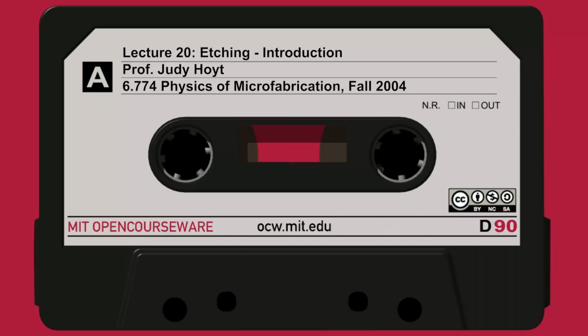So the wafers sit on the smaller electrode. Here the voltage drop across the sheath, instead of being 10 electron volts, is like 100 to 500 electron volts. So 10 times higher at least, maybe more, 20 times higher. So you have much greater energy of the incoming ions. You also have lower pressures to get more directional etching, maybe 10 millitorr.